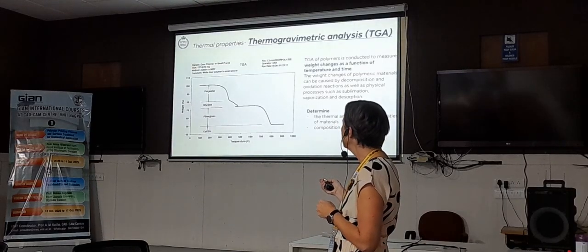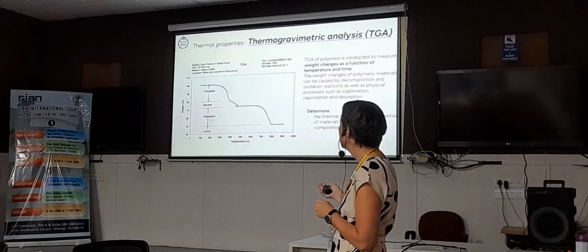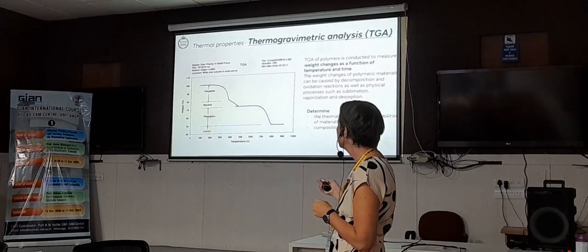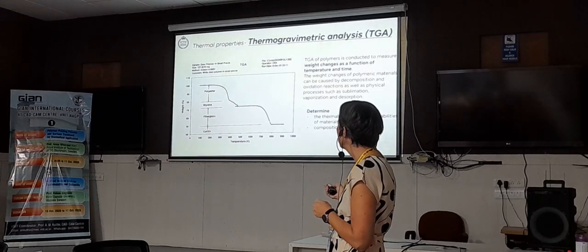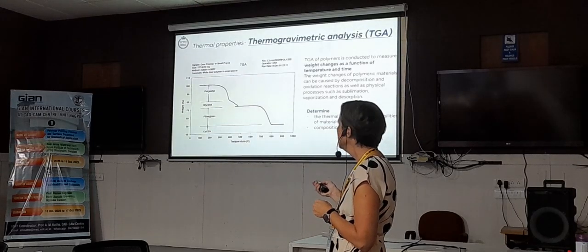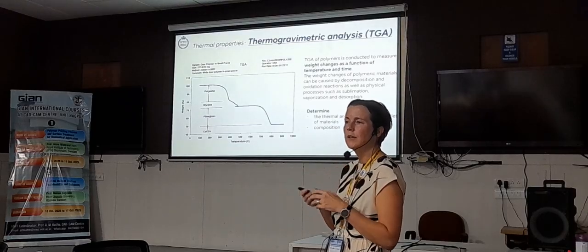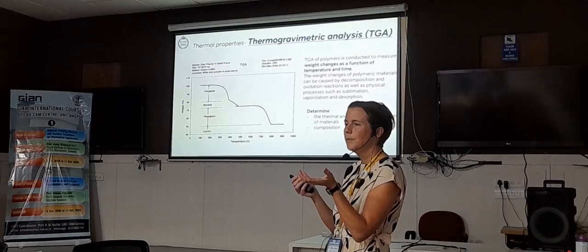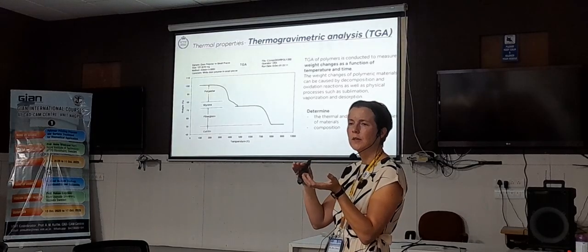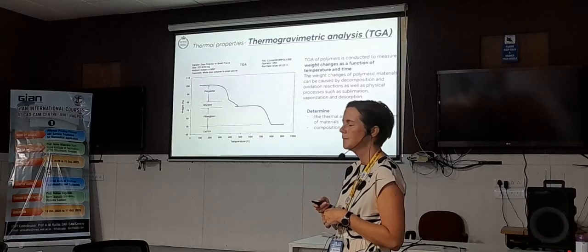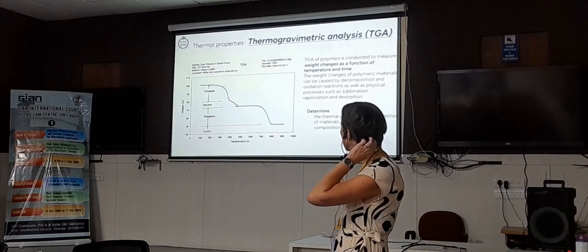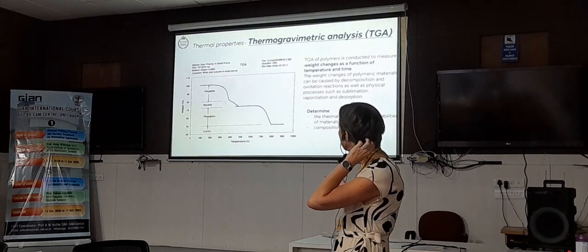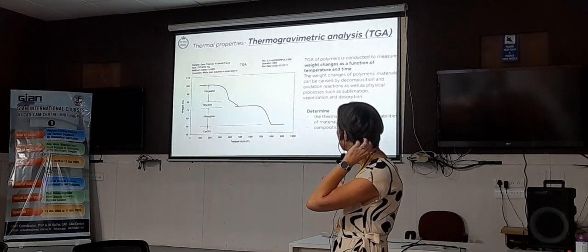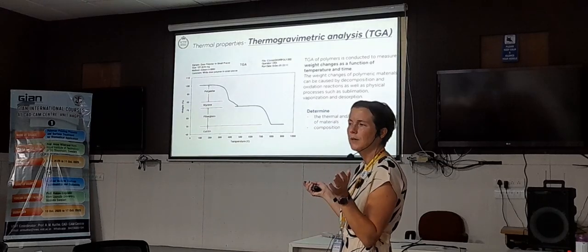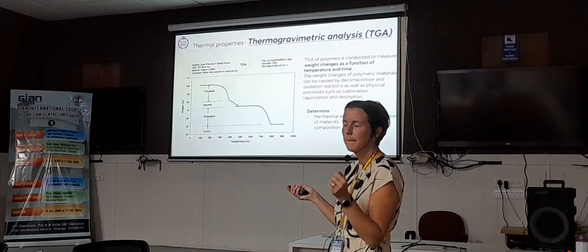In this case, there are different materials. You have polyesters, you have styrene, and you have fiberglass and calcium carbonate. So that's why it starts to degrade at different points. But it's quite easy to do. You just have a cup, you add your sample, increase the temperature, and look into how the weight varies. It's important to know. Say that for the polyesters it's 300 degrees, then you should be below that if you don't want the polymer to degrade while printing.